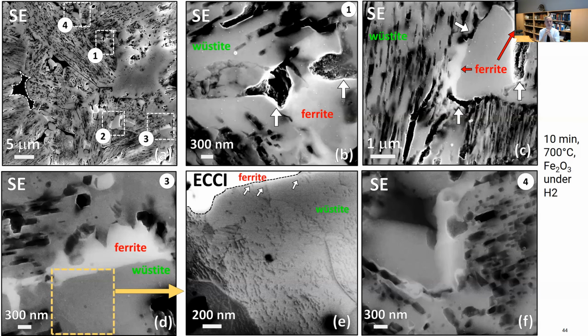I know this. This is from Isnaldi Filho's work, where he very nicely, through the microscope, saw what kind of complex cosmos of defects, damage, interfaces, but also free volume you form when you have, for instance, here a little portion of pure iron that is inside the wüstite, which is the oxide, and you see how through the phase transformation, a lot of mechanical stress is built up and fracture takes place and so on.